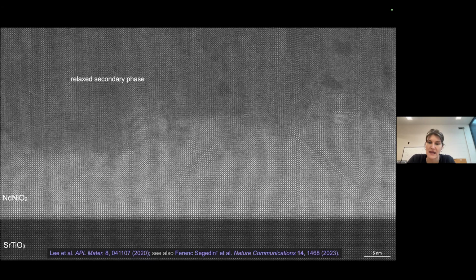And so you can pull on it for a while. That's what you see here. There's a substrate down at the bottom and there's a nickelate film on top of it. And overall, the crystal structure looks pretty good. But as you grow these materials thicker and thicker, eventually the strain is just too much and the material relaxes and stabilizes all of these other secondary phases. You can see all these columnar features coming in. Those are formed as the nickelate tries to alleviate the tension that it was feeling from the STO substrate.